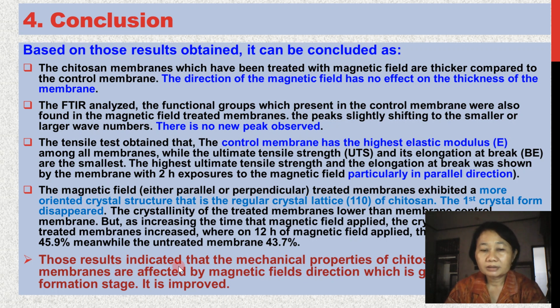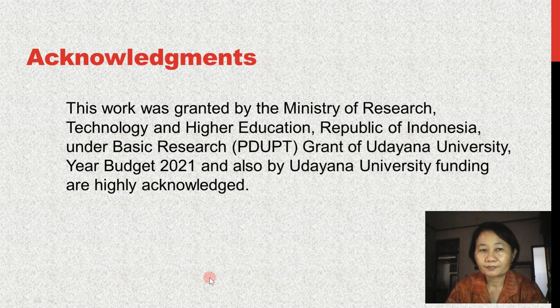This result indicated that the mechanical properties of Chitosan membranes are affected by the magnetic field direction, which is given during the formation stage. It improves the mechanical properties of the treated membrane.